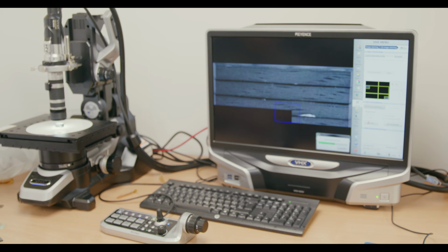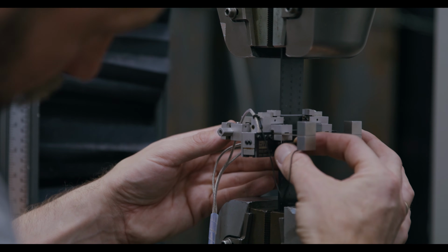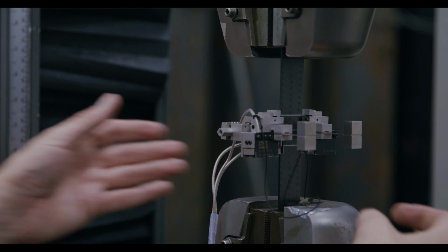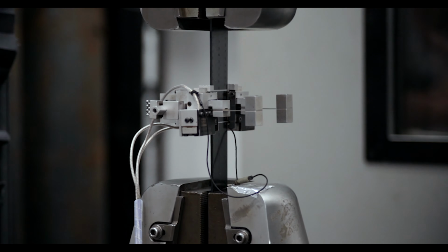Now, in areas that are experiencing very high loads in a particular direction, it's important and advantageous to use unidirectional fibres. So fibres where all of the carbon fibres run in one direction. And we align that with the direction that the part's loaded in to give us the lightest, stiffest, strongest part. When you're trying to design an aircraft, it's all about getting the weight out. You need to deliver just the performance that you need, nothing more, and to do that for the absolute minimum weight.